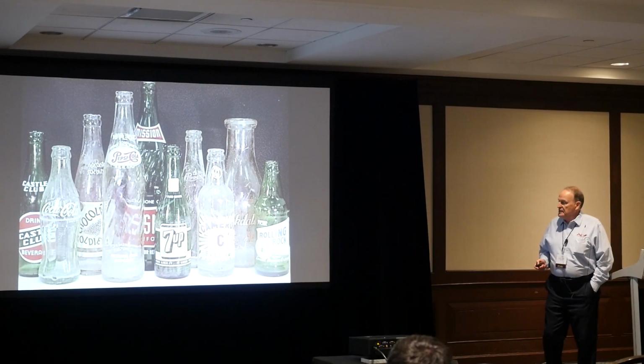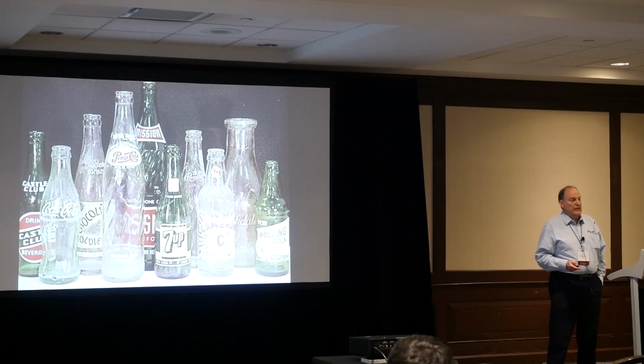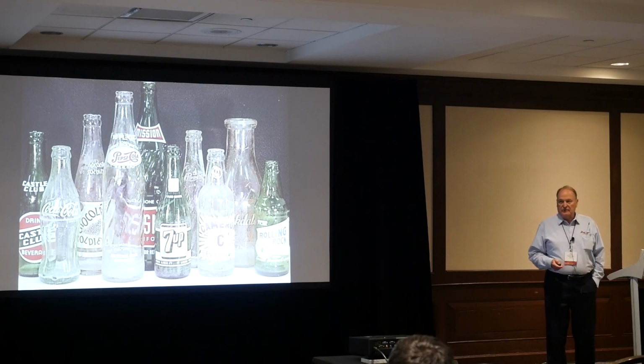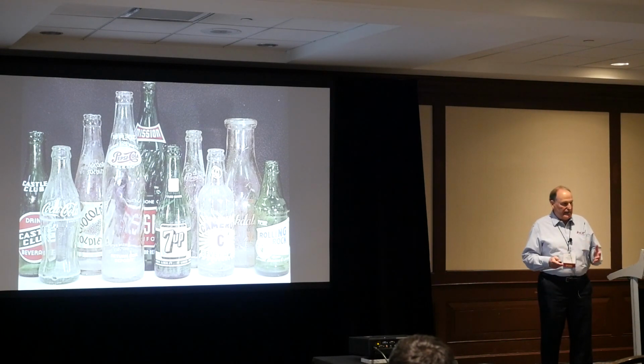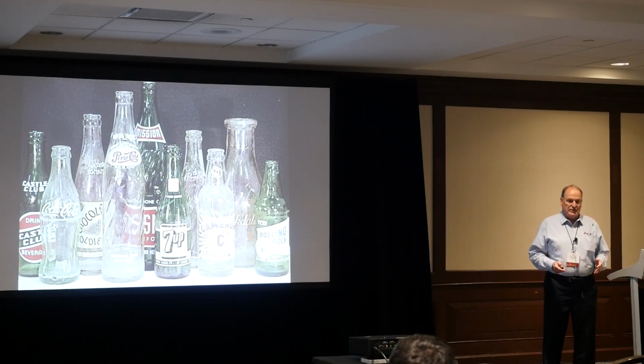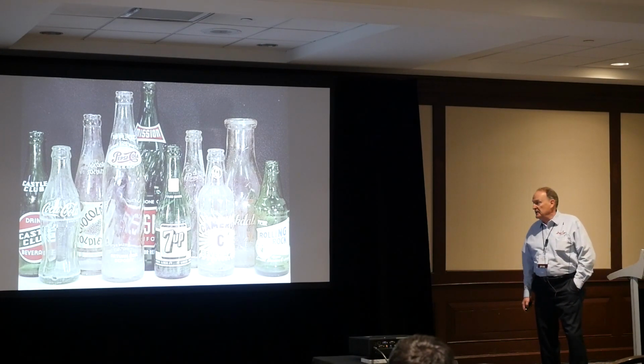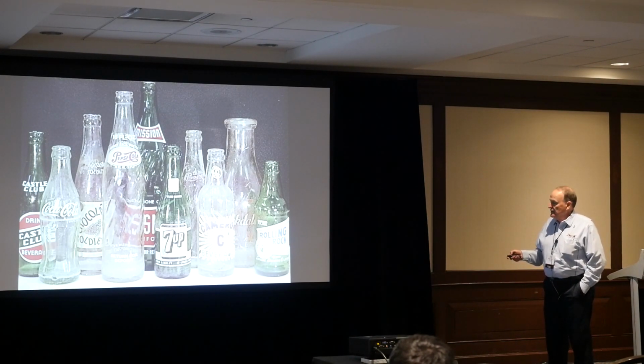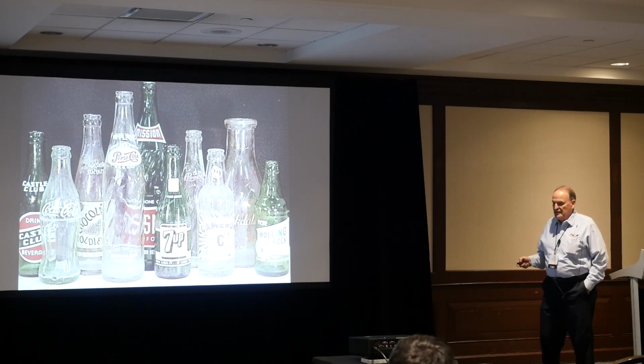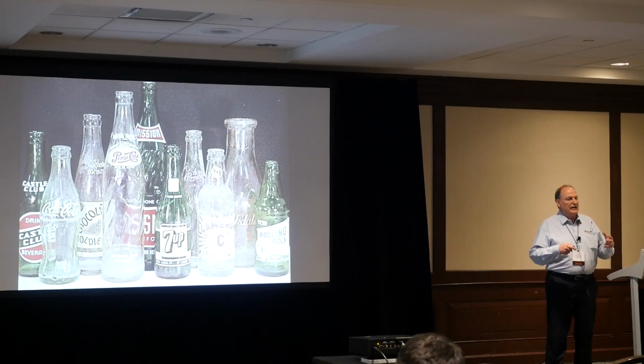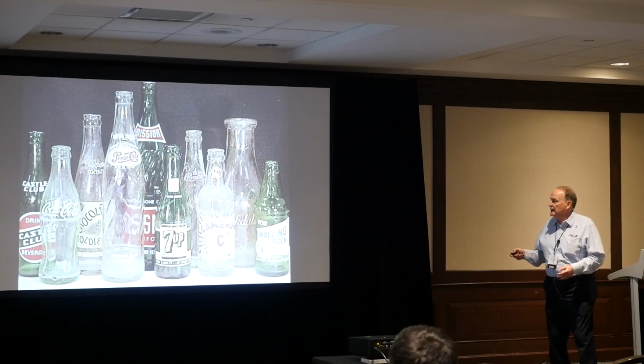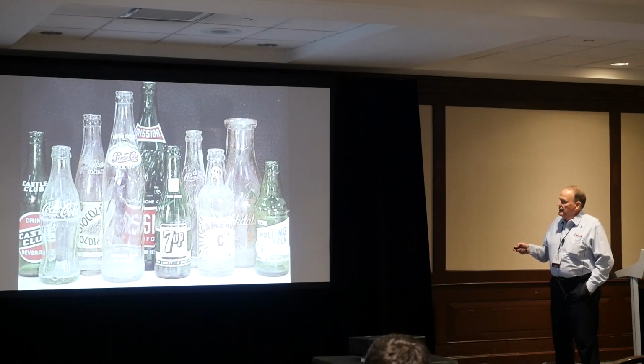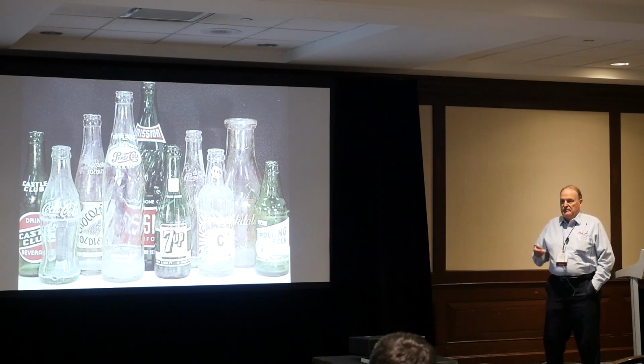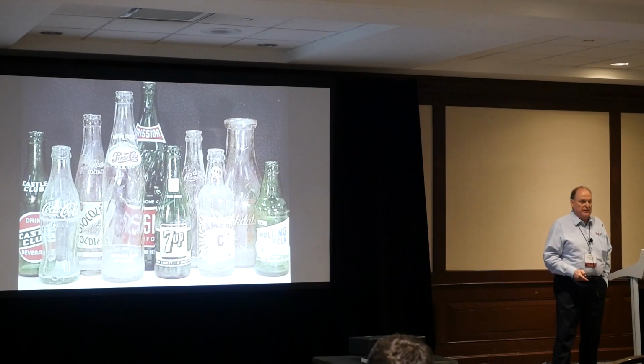The other issue was the integrity of the label itself. Even though these ceramic labels were relatively impervious to the caustic solutions, they still reacted to a certain extent, and the caustic would eventually compromise the integrity. And you can see that here on this 7-Up bottle. The label itself has lost some of its distinctness. The color has started to be muted and faded. And especially up here in the neck, this little 7-Up logo is invisible now. You can't even detect it.